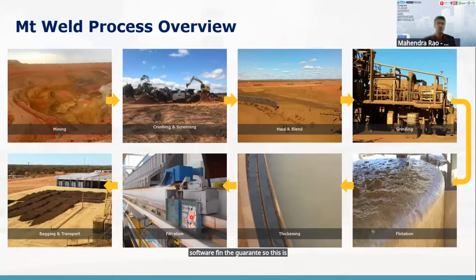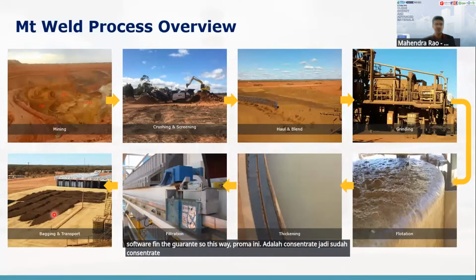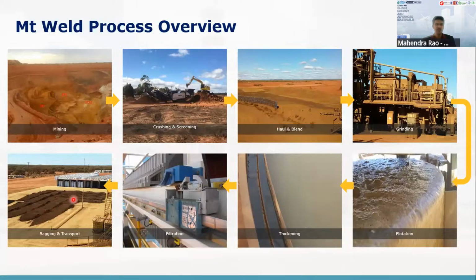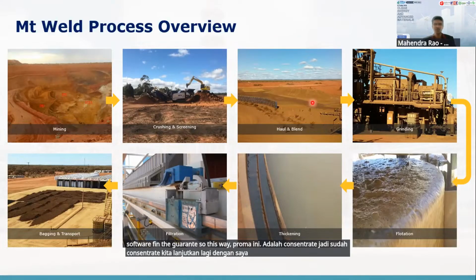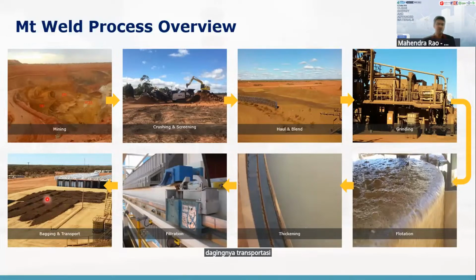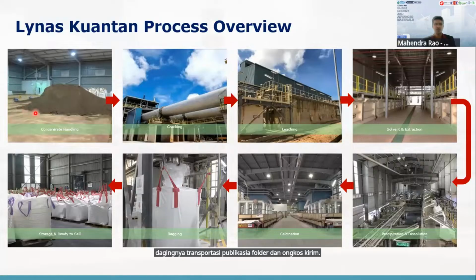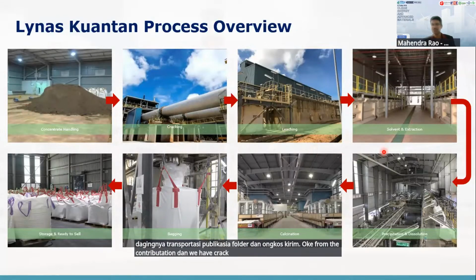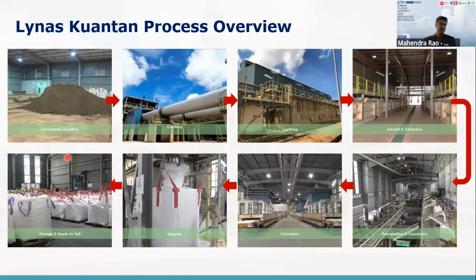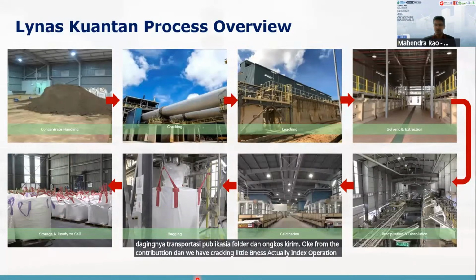So this is what happens at Mount Weld, from mining until we get the concentrate. This is the concentrate, with lanthanum and all the rare earths, a mix of rare earths. This is the upstream process: mining, crushing, screening, and then blending, grinding, flotation, thickening, filtration, and then bagging and transport to Malaysia for the downstream operation. From the concentrate, we then have cracking, leaching, solvent extraction, and then precipitation, calcination, bagging, and storage ready for sale. This is our traditional business in the current operation where we produce rare earths.